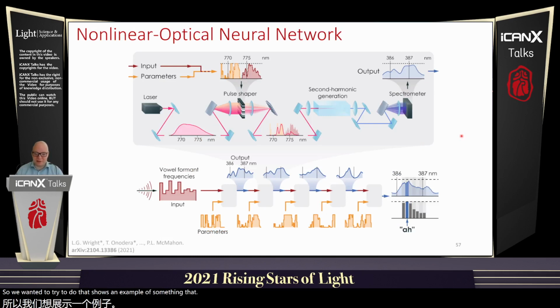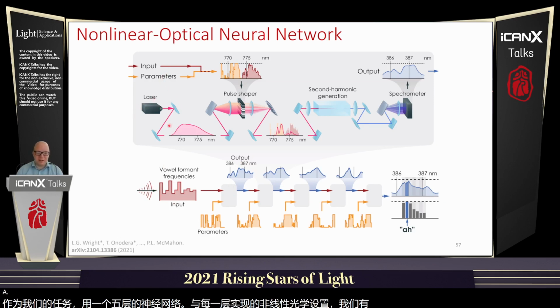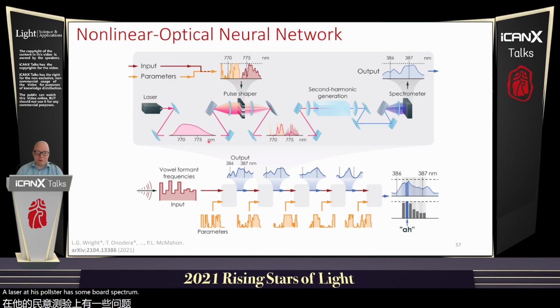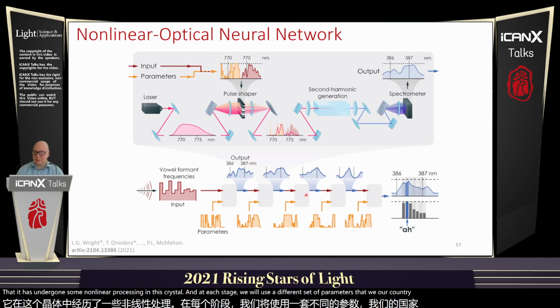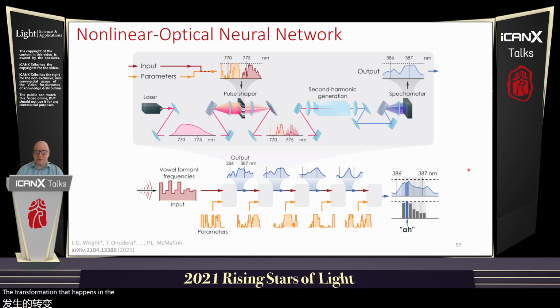Here's an example of something we constructed to do, in this case, vowel recognition as our task, with a 5-layer neural network where each layer is implemented by a nonlinear optical setup, where we have a laser that is pulsed, so it has some broad spectrum. We pass it through a pulse shaper that we use to encode both the data as well as the parameters. And then this gets passed through a nonlinear crystal where a second harmonic generation process takes place. And then we measure the output of this on a spectrometer. And that's the input-output map. We essentially have an input spectrum and an output spectrum that has undergone some nonlinear processing in this crystal. And at each stage, we will use a different set of parameters so that we are controlling the transformation that happens in the multi-layer neural network.